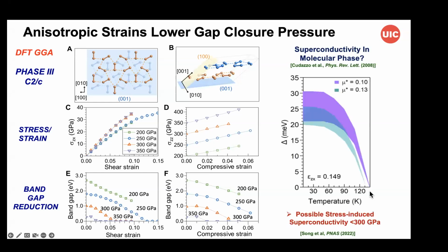So this gives us also the possibility that there is superconducting metallic hydrogen in the molecular forms that are building on the earlier work for hydrostatic compression, that could be possible stress-induced superconductivity below 300 GPa in this system. And this is just shown again using conventional BCS arguments. And here's the calculation of the superconducting gap as a function of temperature.